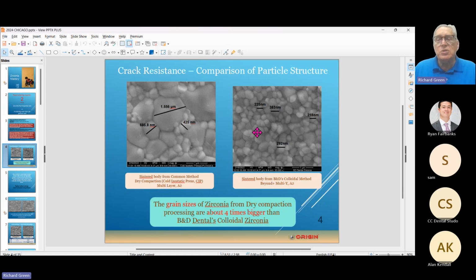If you look at our zirconia, because of the way we manufacture with our colloidal process, you'll see that the grains are fairly uniform in size. They're not exact, but they're uniform, they're small, and this counts when we start sintering zirconia. It can be kind of hard to grasp here, because you're looking at a tooth, a crown that's in your tray, and you kind of think of it as a single chunk of zirconia. But what it really is, is a bunch of grains. That crown may be a millimeter thick. A millimeter is 1,000 microns.